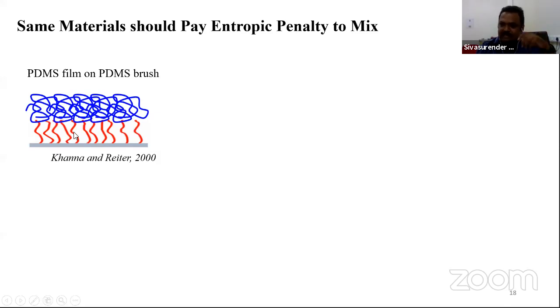And on top of that, they have just put equilibrated PDMS chains where all the chains are performing random walk. And these are two exactly the same molecules with exactly the same chemical nature, right? So they have chosen a very simple system. Because you are choosing exactly the same polymer, there is no difference in terms of energy. You have removed the energetic interactions from the picture, and all that is going to dictate the behavior of this system is the entropy, right?